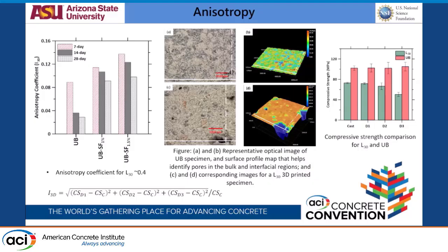For the UHPC mixture, because of that high SP content, the mix flows until it sits on the filament. So it has the capacity to flow into these voids, rather than creating voids, filling up the interfilament and interlayer joints. While for a stiffer L30 mixture, because the shape you place will be the shape you get, there might be voids forming on those joints, so they exist in the sample. So that was one of the observations we saw with these UV mixes, the UHPC mixes, for compression.